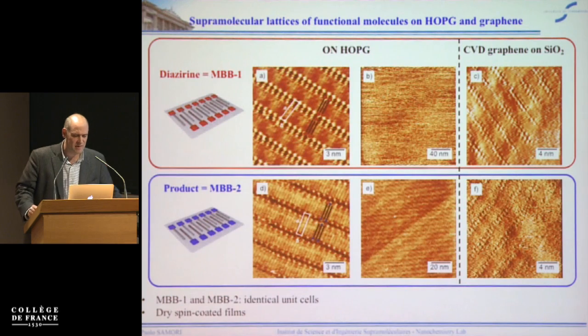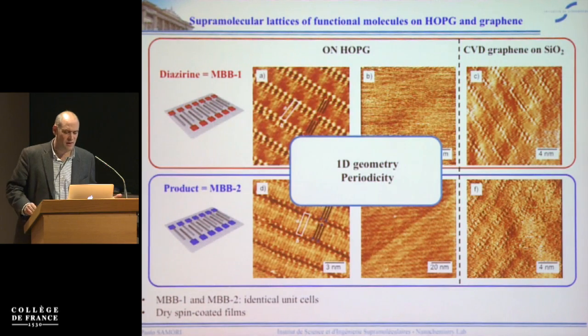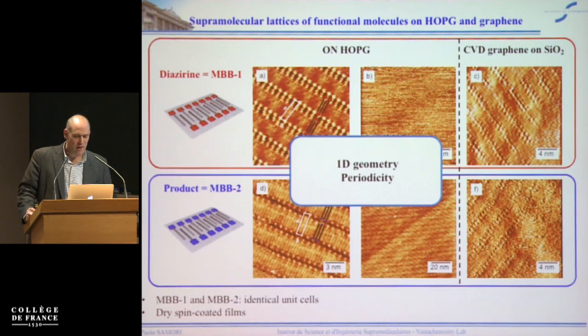And you can see already by STM that we have some nice lamellar structure. Zoom in, and this is a zoom out on graphite. So the area is about 300 by 300 nanometers square. And you can have the same type of lamellar structure also on CVD graphene on silicon dioxide. Here, the surface is a bit more rough, so the images are less nice. I want to stress that the molecules are quite similar, so identical unit cell, and the films were dry, okay? So what we have created here essentially is 1D geometry, and we obtain some periodicity in our structure.